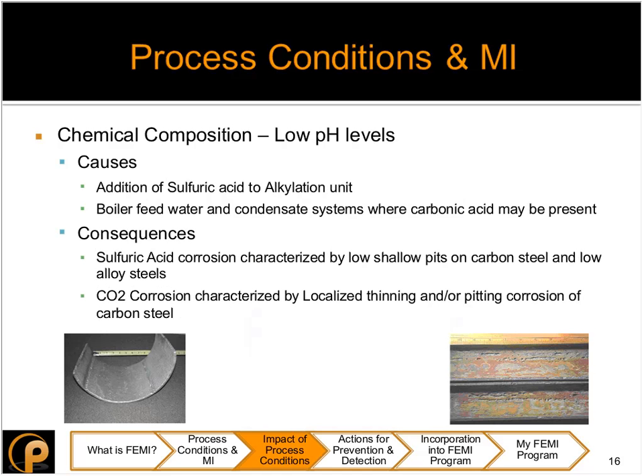So what you can have is sulfuric acid corrosion, which is characterized by low shallow pitting on carbon steel and low alloy steels. The image on the bottom left corner gives a pretty good example of where sulfuric acid corrosion has created grooves on this metal right here, as I can show you on the image. That is another type of failure that can happen.